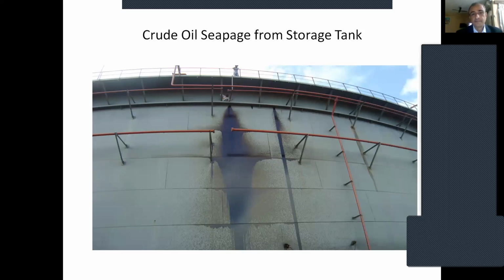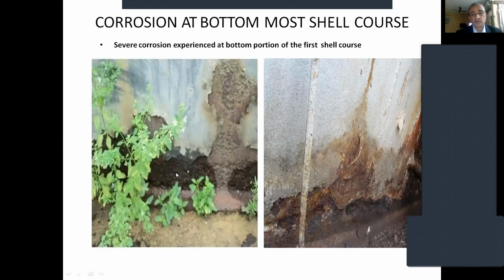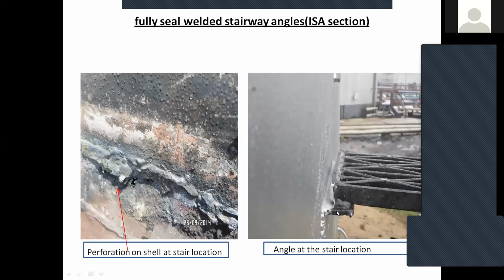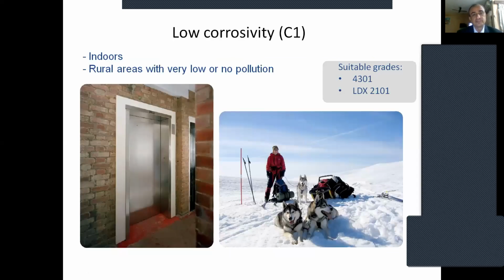So this is another form of corrosion. It's a leak seepage from the storage tank. It's severe corrosion at the bottom of the tank, first shell course, see this corrosion. This staircase is also broken down during the service life itself. Within 4 or 5 years, the staircase or the shell gets perforated by the seawater chloride content. So right selection of material is most important for the engineer to suggest.